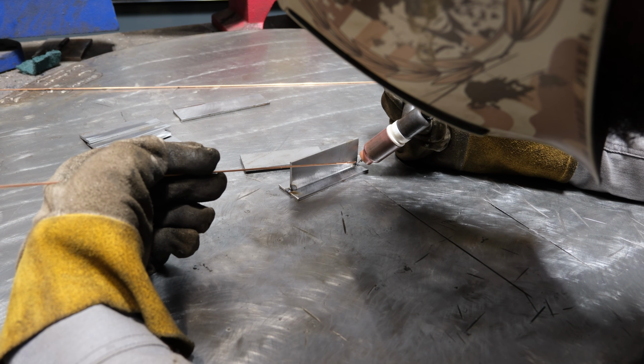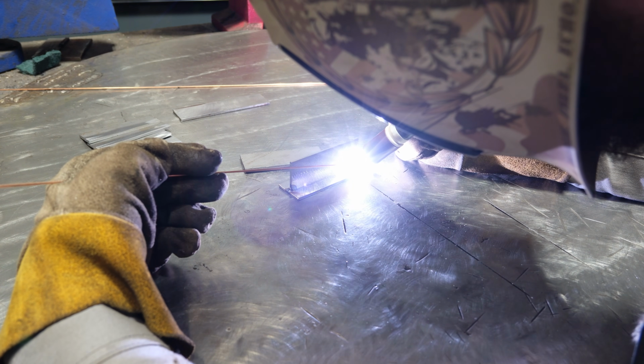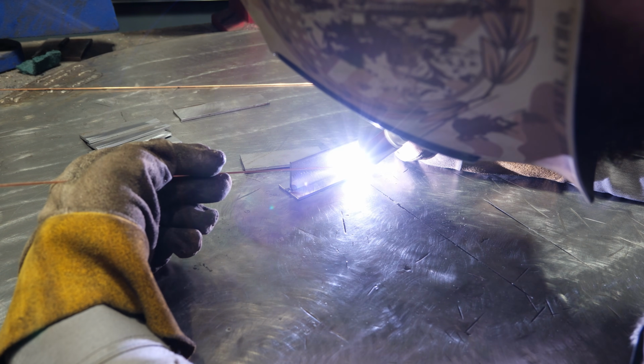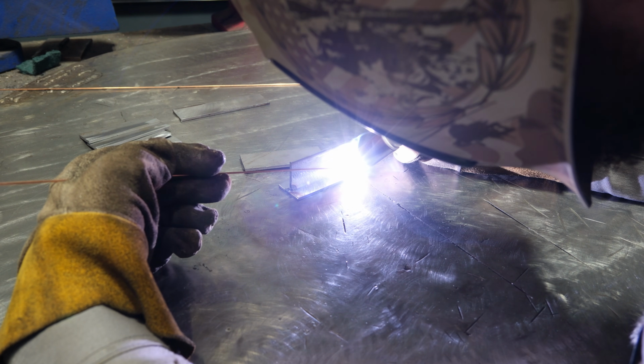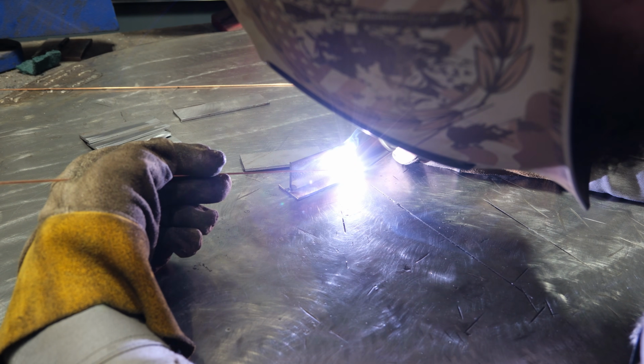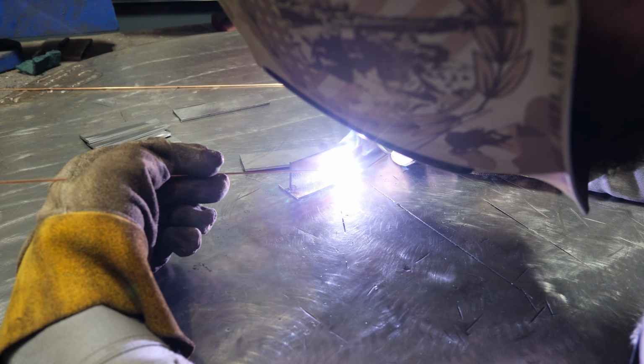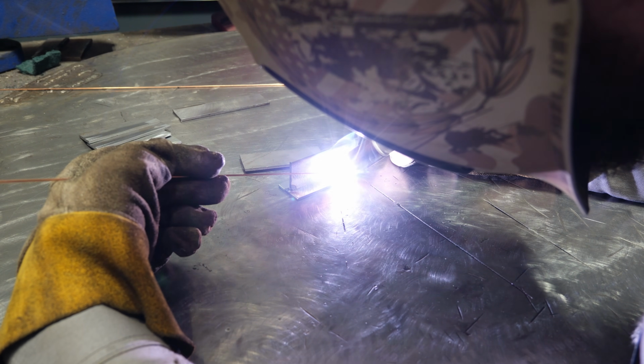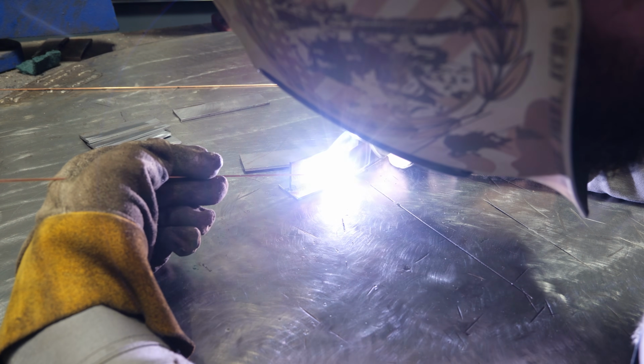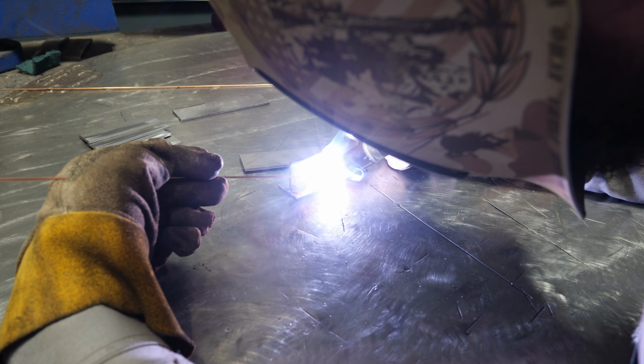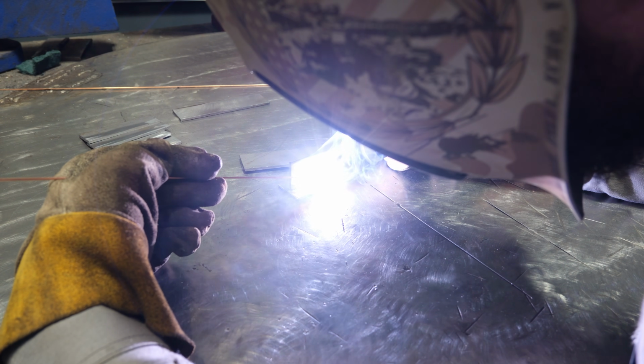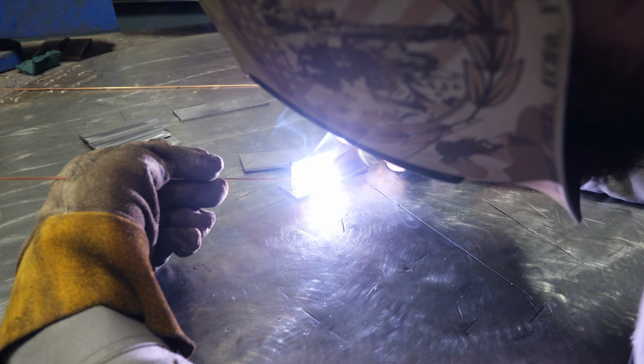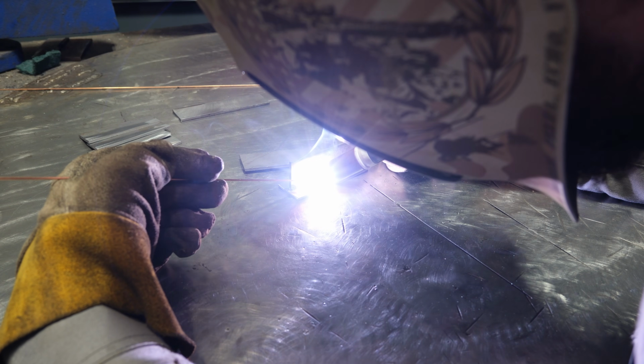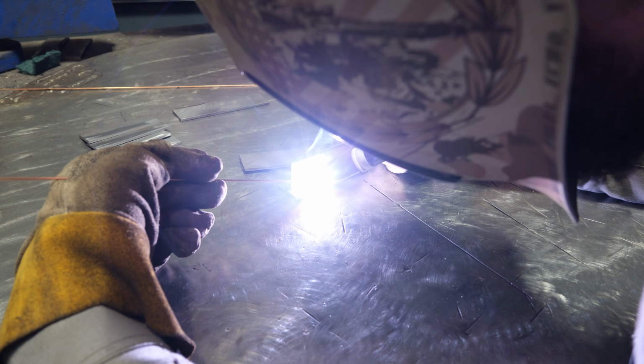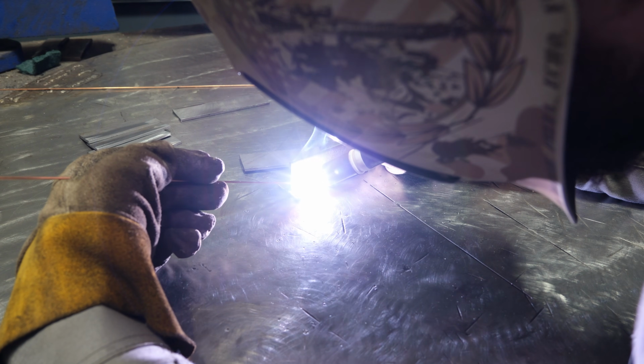So now we're going to watch me in real time weld this joint out. And one of the things I want you to pay attention to is how I'm just dabbing the filler with my left hand and I am not feeding anything. This is very common for new TIG welders that don't know how to feed properly, that they just dab into there. The problem with doing this is it's going to produce a very concave bead, and that's undesirable because the throat depth of that weld is going to be very thin, and unless you go back and fix that with another pass, your weld is going to be weaker than it should be. Don't get me wrong, it'll still have strength to it, but it's not anywhere near what it could be. And again, I'm not feeding it, I'm just dabbing it.